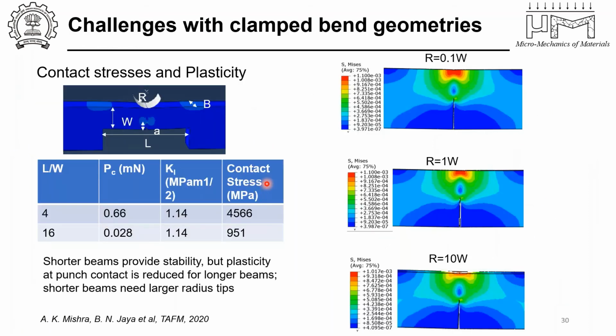So does it mean that there are no problems with this geometry? Clearly no, there are challenges. One thing is about using the right kind of punch. Many people end up using a Berkovich tip or a cube corner tip to do these kinds of microscale tests. But what you should ideally use is a wedge tip with a particular radius, and the radius of that tip will also depend on whether you have a low yield strength material or a high yield strength material, and whether you have a low aspect ratio or a high aspect ratio of the beam.